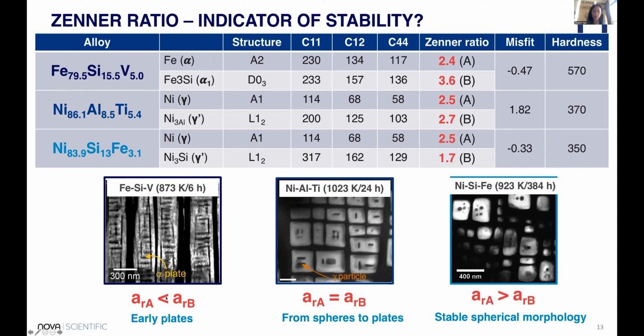If the Zener ratio of the host phase is smaller than that of the hierarchical particle phase, their morphology will be plate-like, even in a very early stage of aging. If the Zener ratio of the host phase is similar or equal to that of the hierarchical particle phase, the morphology will initially be spherical and eventually transform into plates. If the Zener ratio of the host phase is larger than that of the hierarchical particle phase, their morphology will be spherical and stable over long aging time.